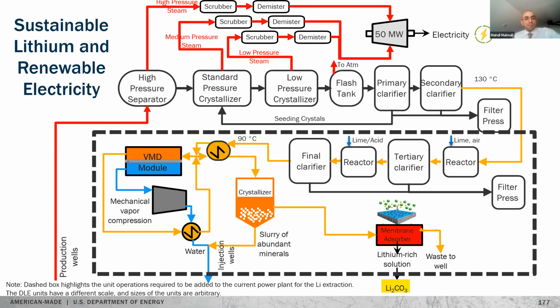This module is something that we have demonstrated. We can make it almost commercially available. It's being tested in a pilot plant for oil and gas produced water business. So essentially the driving force with this type of membrane process is not pressure. So we are not having those difficulties with all the pressure-driven membranes. There's no osmotic pressure limitation. Here, as long as the brine is at high temperature, the water vapor will diffuse through the membrane and we will collect it on the permeate side.